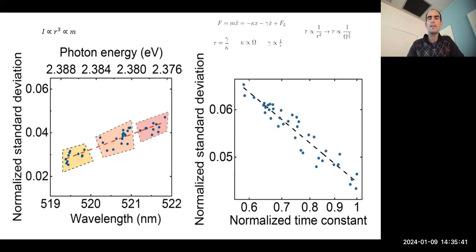You can also figure out the size not only from the amplitude of that noise, but also the time constant - what is the characteristic decay time if you do an autocorrelation? That also tells you about the size, since it's related to drag as well. So there are two ways of getting at the same information, and we can figure out the size of the particles and relate that to the quantum confinement.